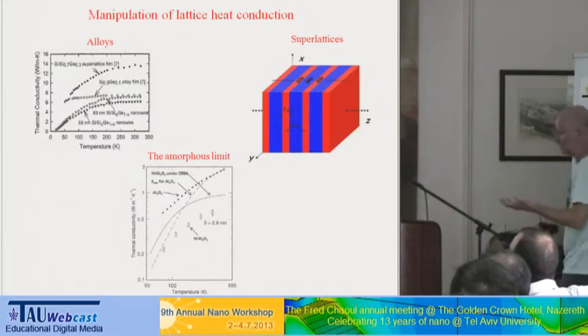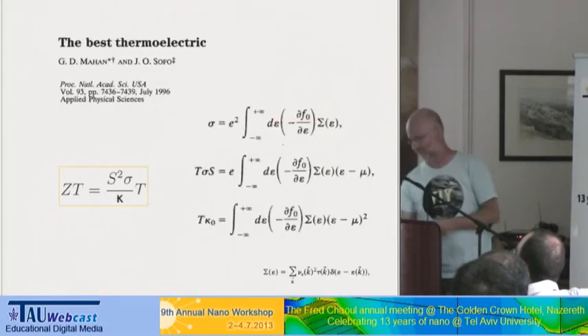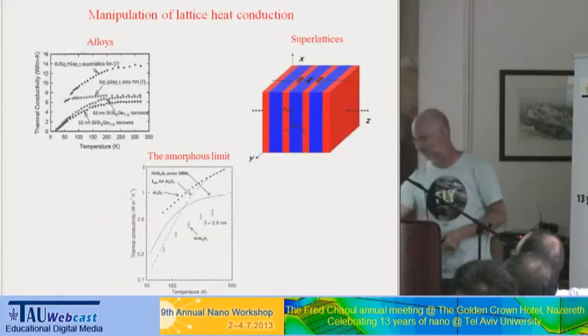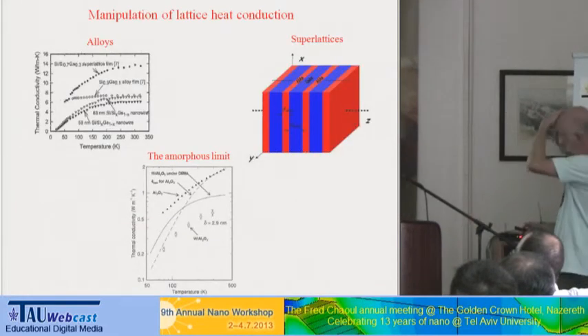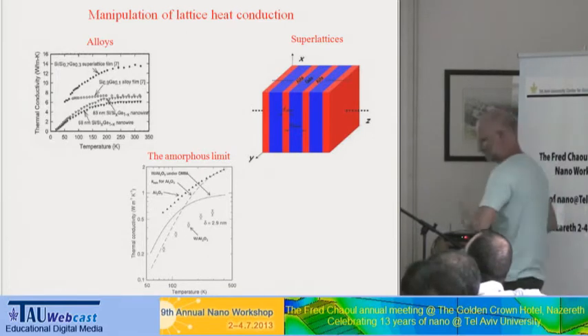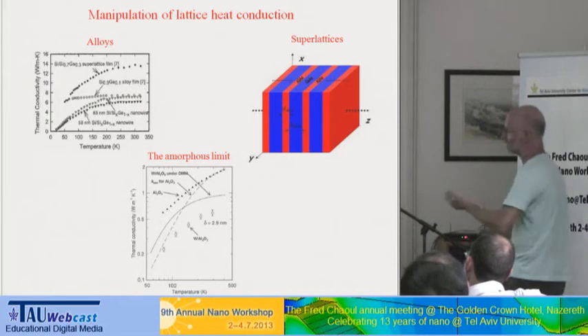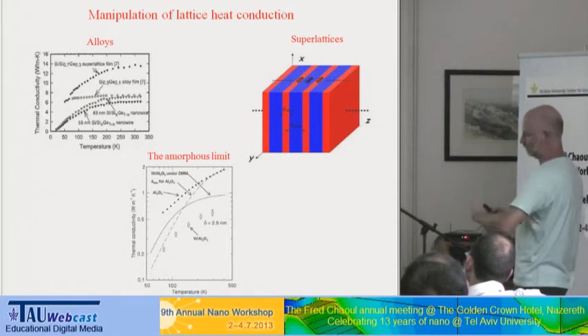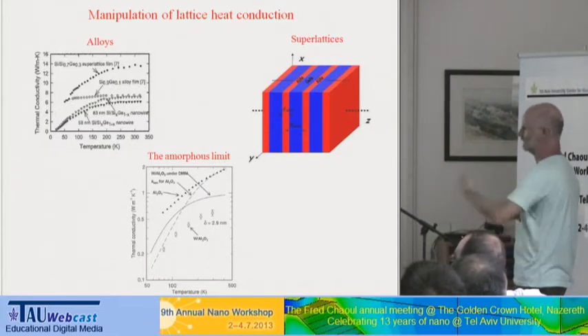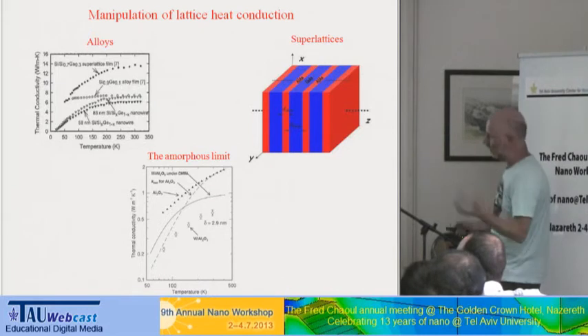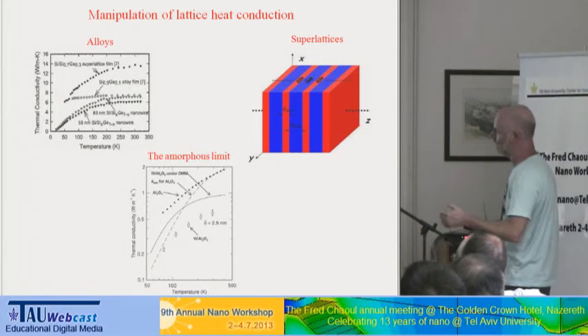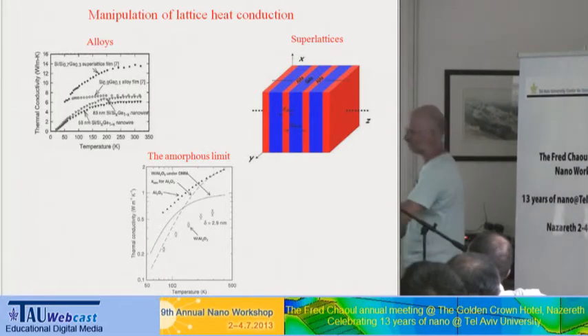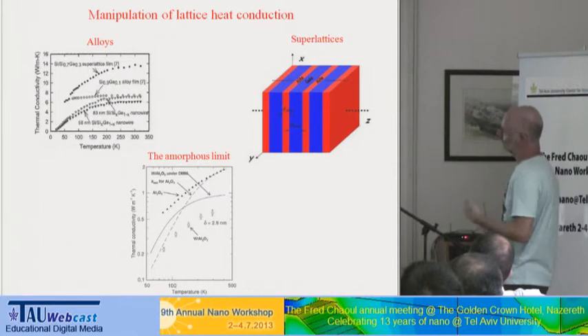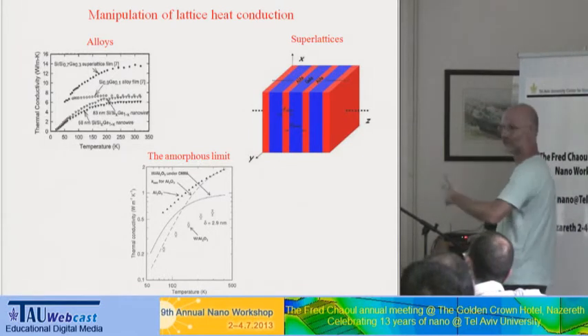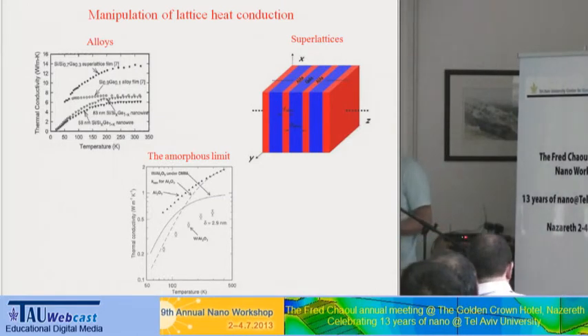What people actually prefer to do is to work on the other side of the equation, so to manipulate the thermal conductivity, or more importantly, the lattice thermal conductivity. So they either work with alloys or with superlattices, and in both cases, you simply block the way that the phonons are propagating efficiently by changing the structure. If you have a mismatch in the crystal as the phonons are propagating, they bounce back, so the thermal conductivity is not efficient. And it's obvious that once we get to the amorphous limit, once we have a material that is completely amorphous, then the lattice thermal conductivity is going to be at the minimum, but then it's really difficult to make materials like this that are also very efficient in terms of electrical conductivity, so this is a problem.